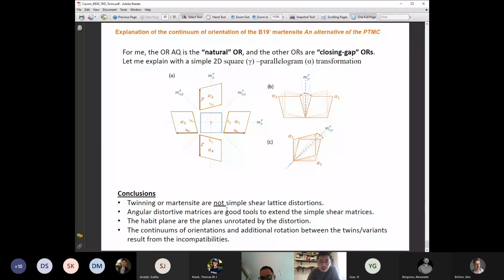So I think Song raised his hand. So please, Song. Yeah, thank you very much, Jingwei, and thank you very much, Dr. Karen, for a very nice presentation. So I have a follow-up question about the continuation of rotation. Does it result in a gradient of dislocation? Because we have a continuum rotation of atoms. It tends to result in a kind of lattice strain, and that requires necessary dislocations to accommodate that rotation. And if that's the case, do you see that in the EBSD mapping? Because when we do EBSD, we tend to see this gradient of dislocation pattern, necessary dislocations. So that is two follow-up questions.